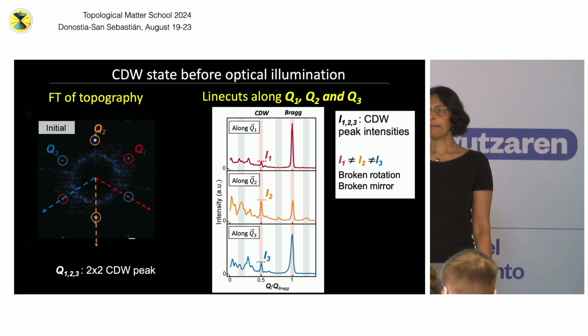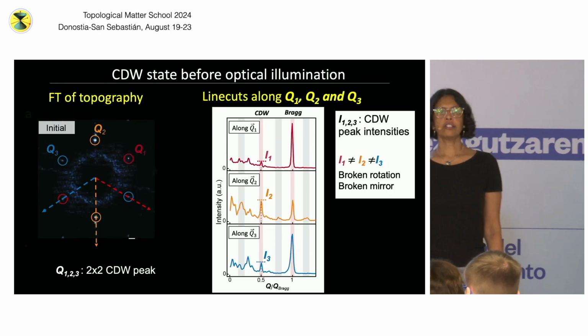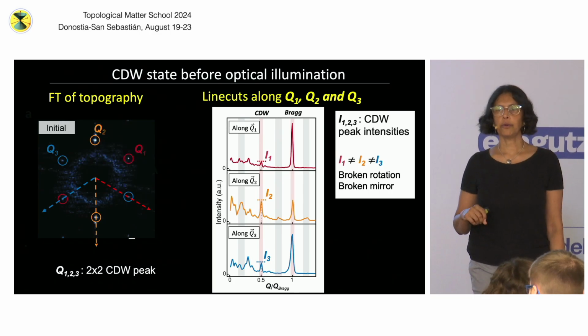The thing is, mirror symmetry is also broken. This peak and this peak are not the same intensity, so that's a bit surprising. And I'll show you later from our data, we believe that the reason these two are not the same intensity is not anything intrinsic to the sample. It's because the sample is extraordinarily sensitive to strain. The smallest strain in the sample can actually change the intensity of the CDW peaks.